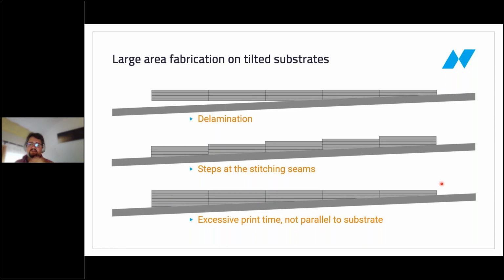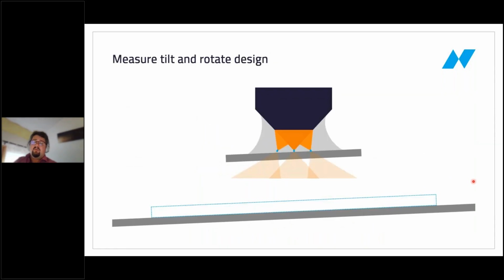So this is also quite far away from being a perfect solution. We implemented this a little differently. Mechanical would have been an option, and we've just seen that this can offer some great results. We went down a different path. Still, of course, you have to measure your tilt. In our case, we do this by doing a multiple spot interface find. So now we know for the individual print field whether or not we have a tilt and how big the tilt is. And now we just rotate the whole design before slicing it.